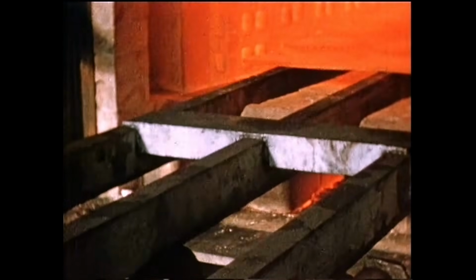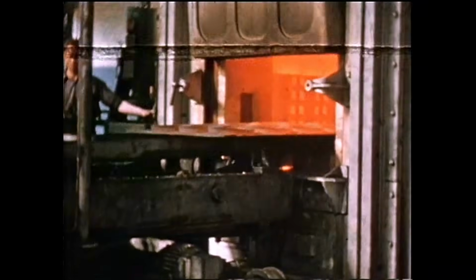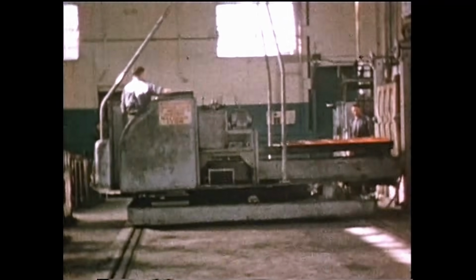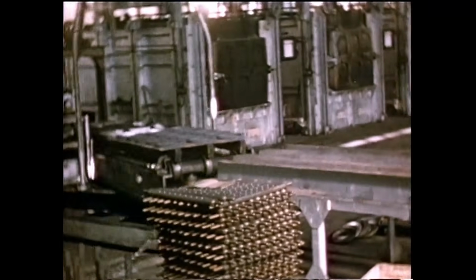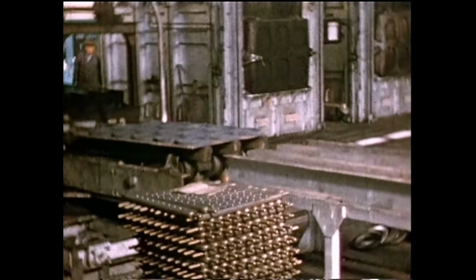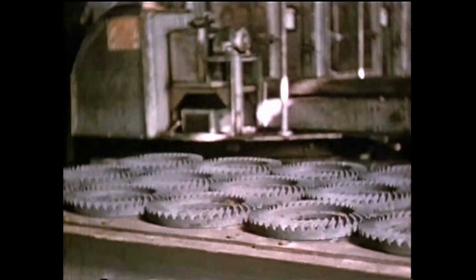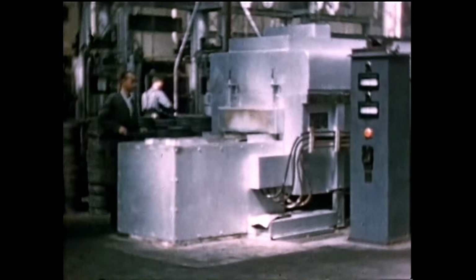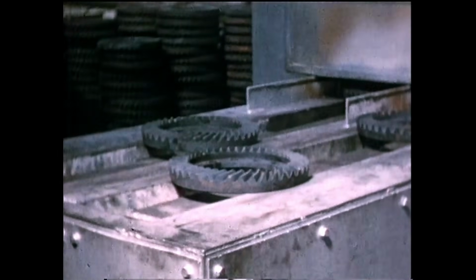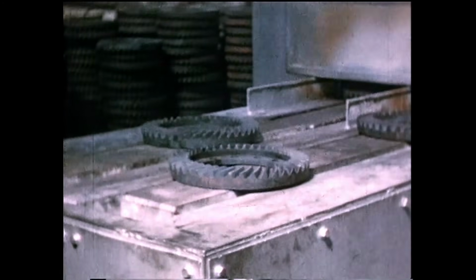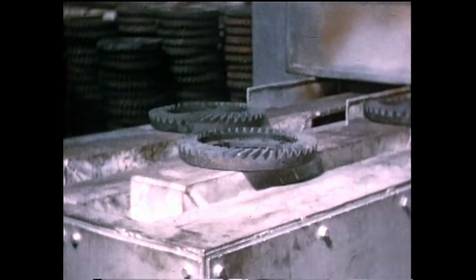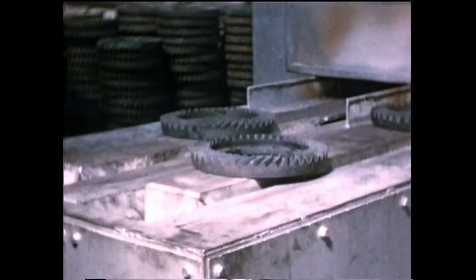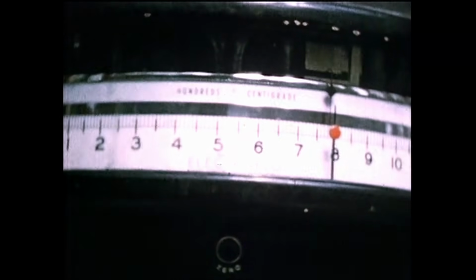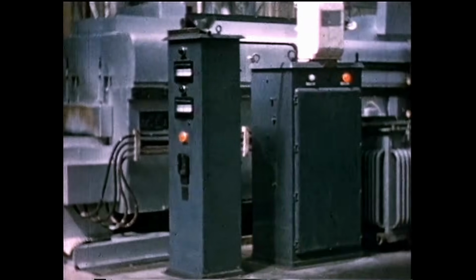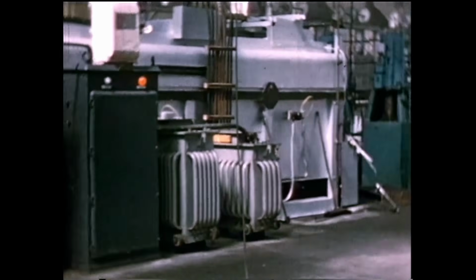Returning to the crown wheels, these are withdrawn and left to cool in the air. Next comes the hardening process. The parts are placed into the walking beam conveyor, which feeds the work continuously through the furnace. This takes approximately 1 hour, during which a constant temperature of 780 degrees centigrade is maintained. These combined treatments will ensure a very hard, wear-resisting outer surface to the teeth, combined with an extremely tough inner core.